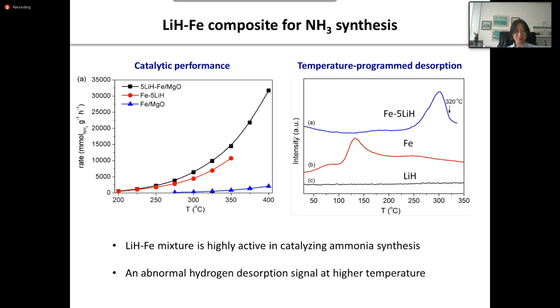However, an abnormal observation is that when we mix lithium hydride with iron, we use this as catalyst. We found that this mixture can catalyze ammonia very well. And at that time we very much wanted to know what happens on the surface, because it's a mixture. We cannot see any new phases there. So we conducted a temperature programmed desorption, and we did observe a hydrogen desorption at around 300 degrees Celsius. This hydrogen desorption is very different from neat iron or neat lithium hydride. So that's something very different at the surface.